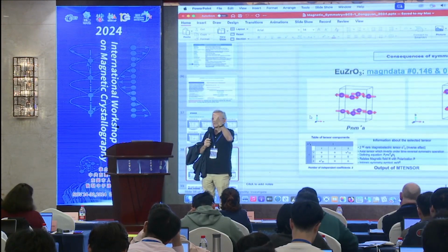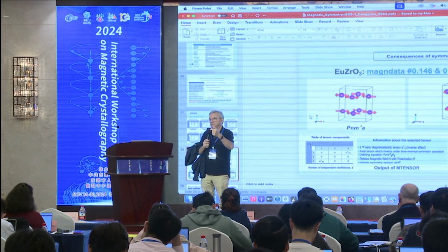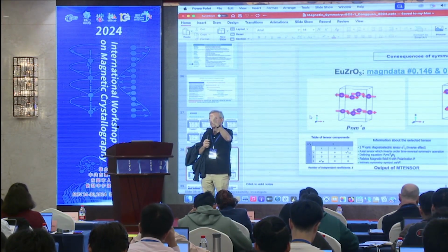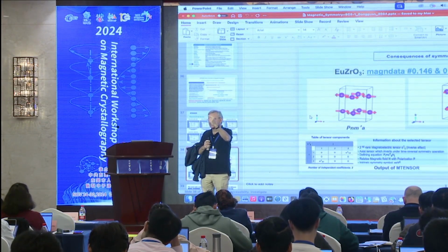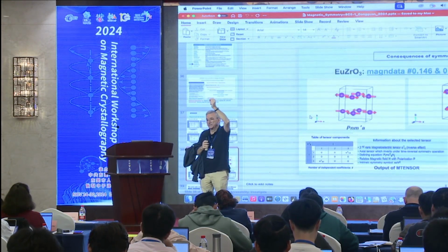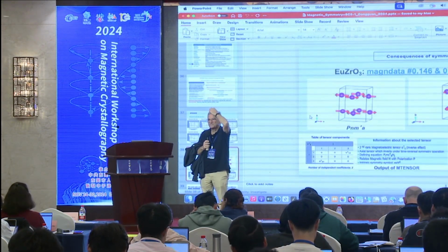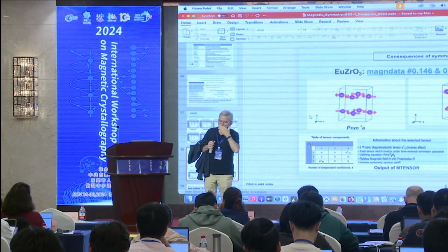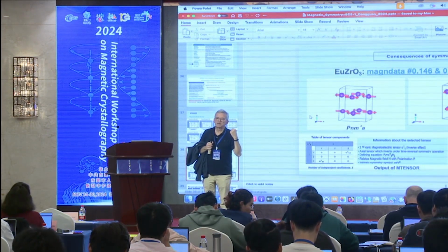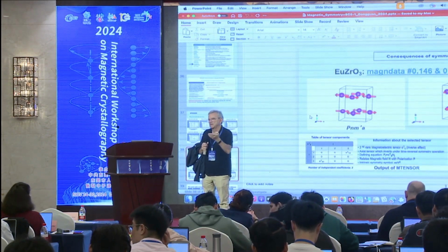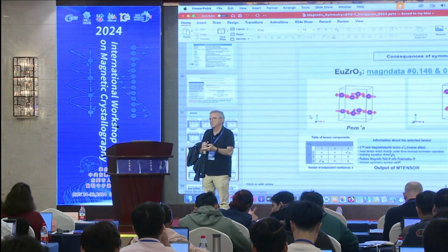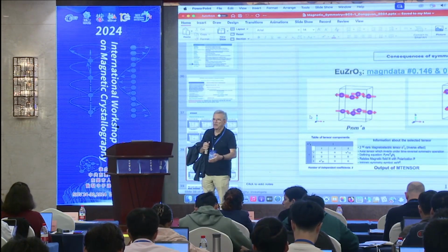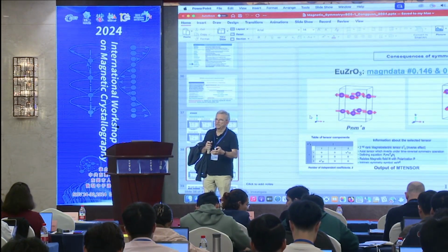And some atoms have split it. So your asymmetric unit in this magnetic CIF file will have, in many cases, atoms which are symmetry related between them in the parent phase. I see, so we lost some of the symmetry. Yes, you always lose some symmetry, but in the case of the simple examples that I've shown, Pnma and so on, it is a k equals 0 with propagation vector 0, so the unit cell is the same, and you don't lose any parent space operation.